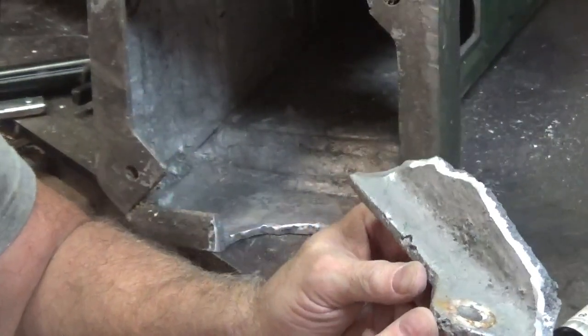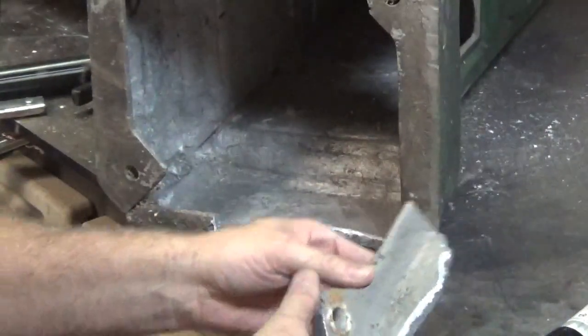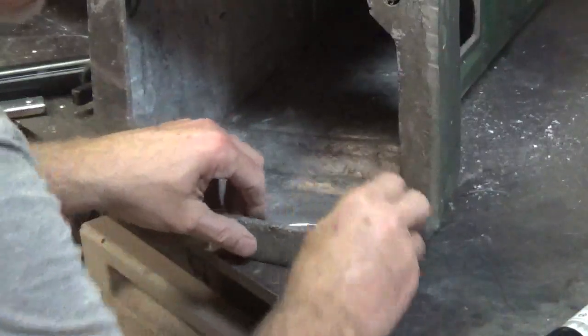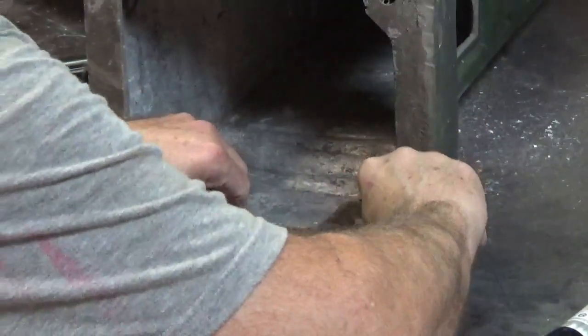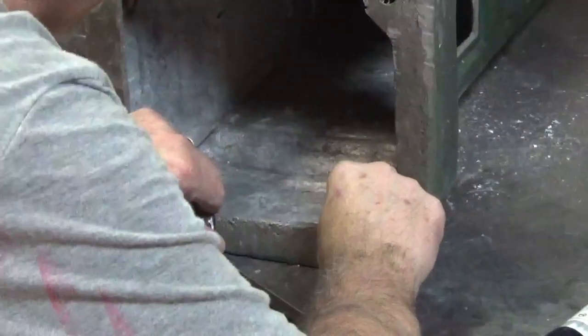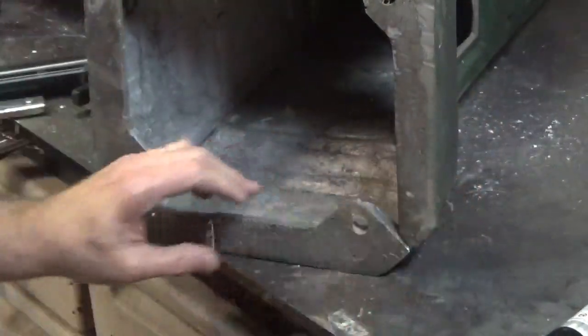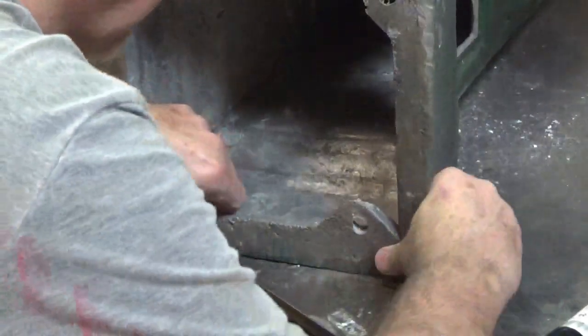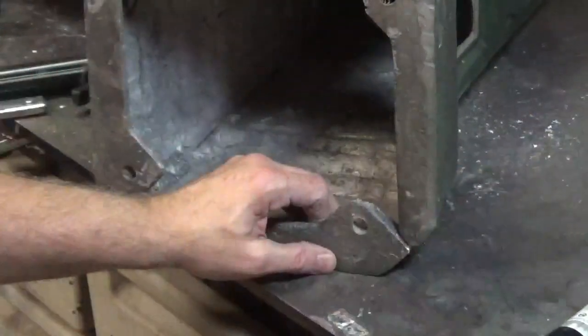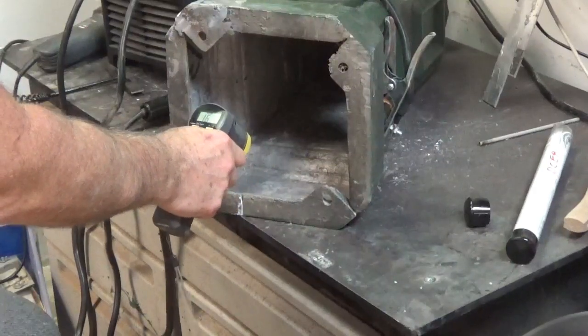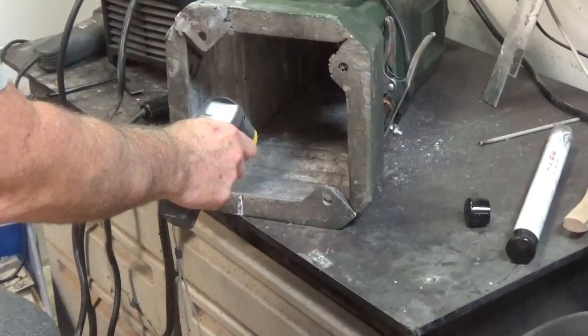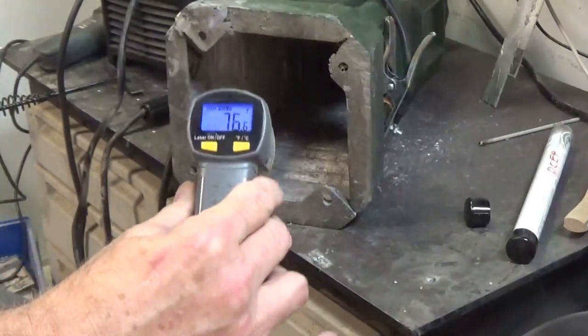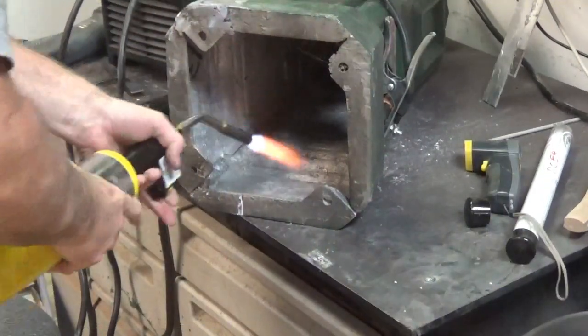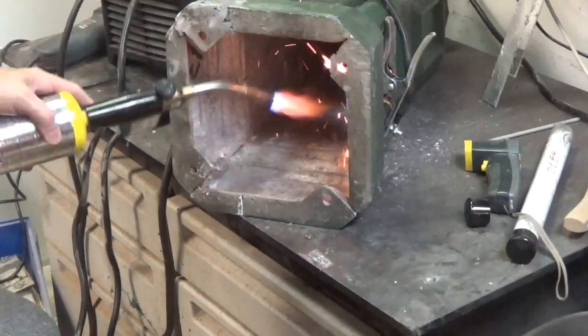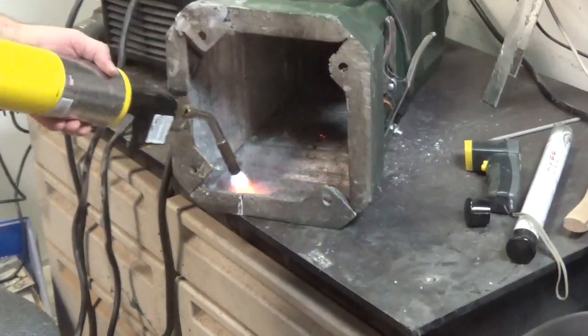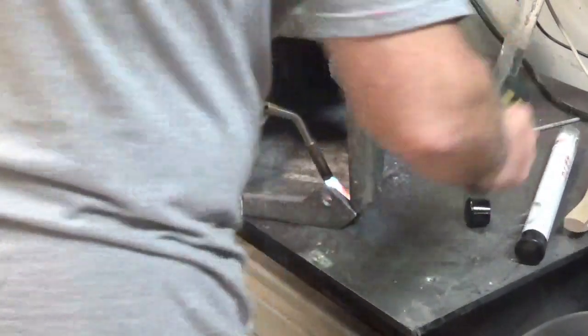So I'm going to try the old technique of putting a bevel on it and see if I can fill that in with these rods. Now this is varying thickness. This is from 1/4 inch to close to 1/2 inch in spots. So it's a little tricky to weld. There's no uniformity to it. So I'm gonna preheat this thing, and I'm gonna try to get it up to 250 or 300 degrees. That's an awful lot of aluminum to heat up, but we'll see how that goes. I'm just using a MAP gas torch, and gonna hope for the best.